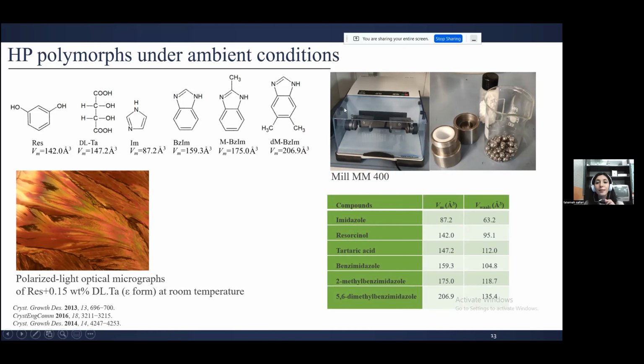Why I add the milling here is because, as you know, in the pharmaceutical industry, for making tablets, they have to use milling. And we know that many drugs and compounds in this step will transfer to another phase. So just for checking, I also checked the mix of tartaric acid and resorcinol by milling without any heating, to see whether it would transfer to epsilon or not. It was alpha after checking by powder diffraction.